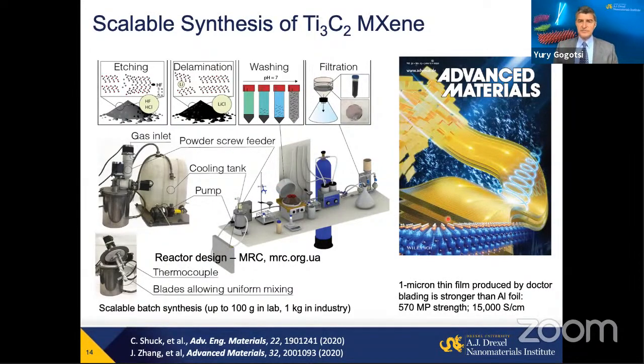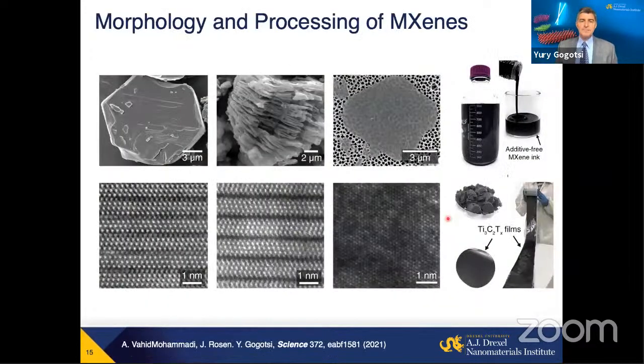And you can basically take the material from the synthesis and washing, and often directly process it into a film. So we start with a ceramic powder, like you see one here. Those are Ti3C2, for example, layers. You only see titanium, you cannot see carbon here, connected by a monatomic layer of aluminum. You etch the aluminum away, say in hydrofluoric acid or lithium fluoride and HCl solution, and you can see that the surface becomes terminated now, and aluminum is gone, but the layers of Ti3C2 did not change. After that, you can exfoliate it by intercalating, just like you would exfoliate many other two-dimensional materials, because now there are weak hydrogen or van der Waals bonds between the layers, and you get these single-layer flakes.